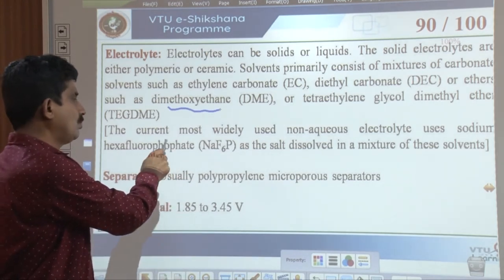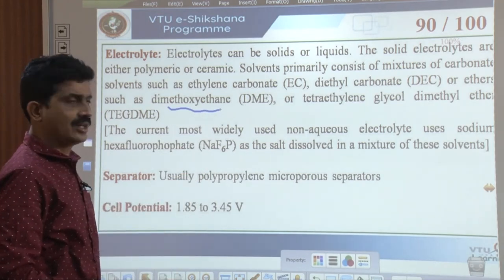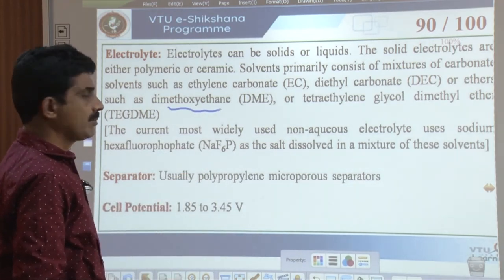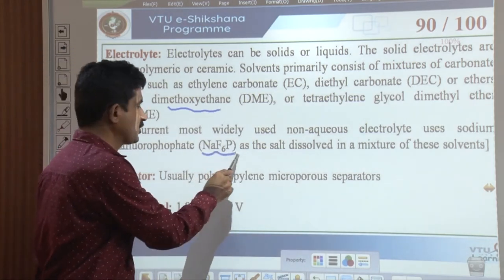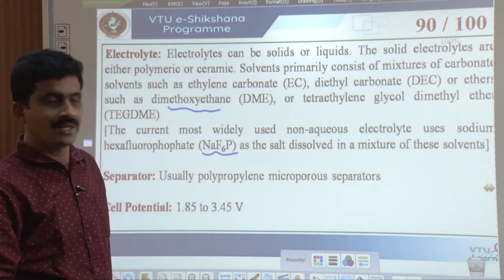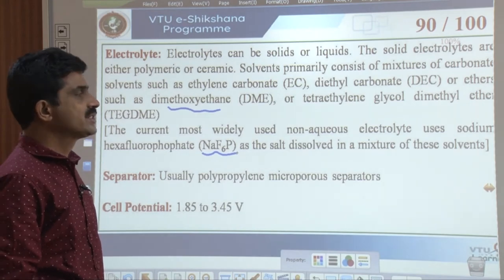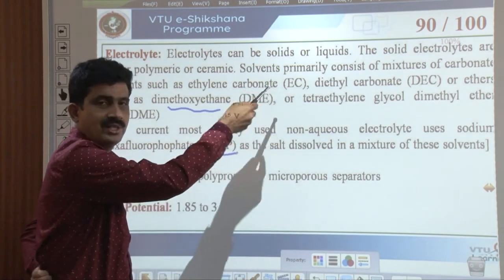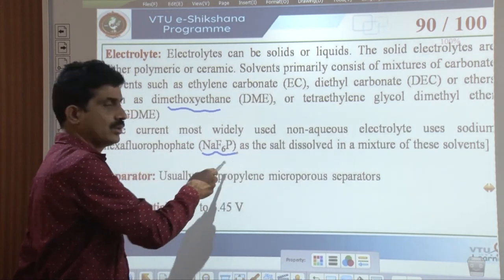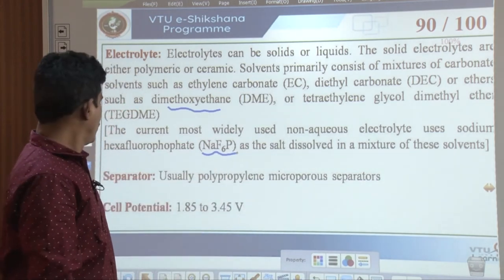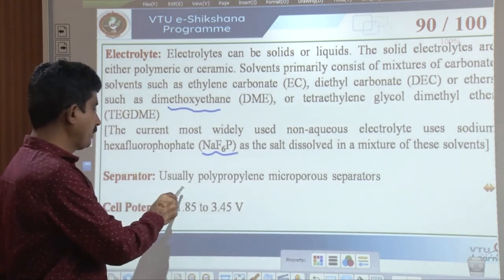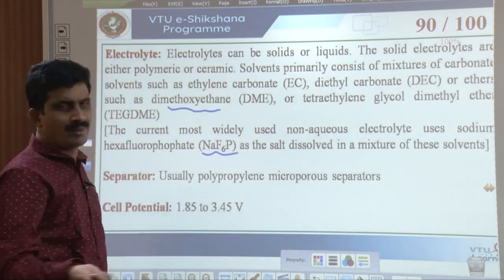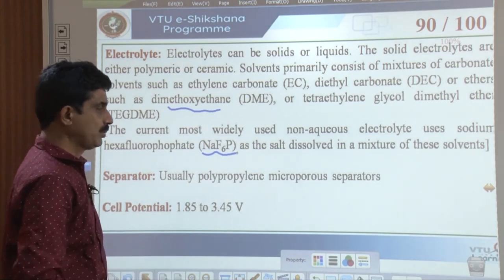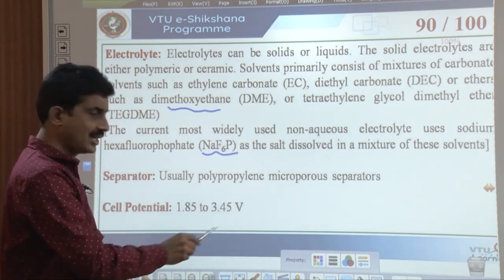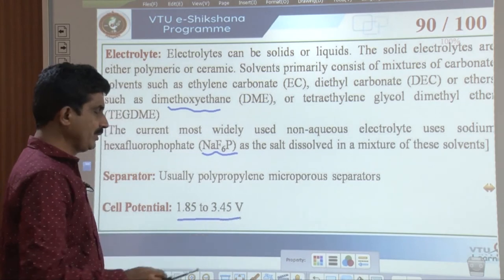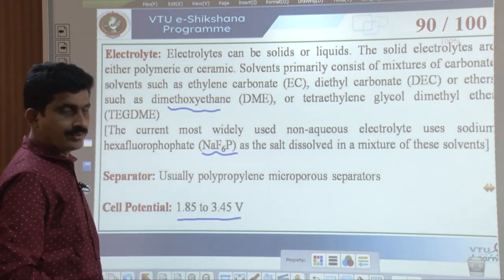Then the most widely used non-aqueous electrolyte in a sodium ion battery is sodium hexafluorophosphate, NaPF6, dissolved in a mixture of these solvents. So these solvents are mixed and this electrolyte is dissolved in them. Then separator, usually a polymeric material, polypropylene microporous separators, and the potential is from 1.85 to 3.45 volt. Okay.